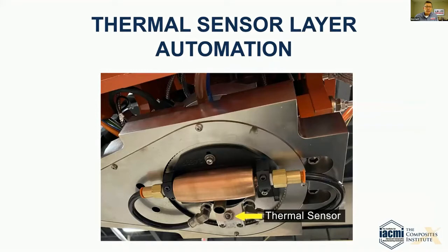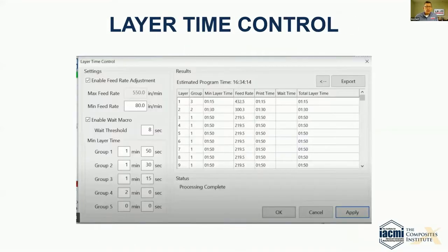And what this is, they use a small thermal sensor that is right in front of the nozzle as it's depositing material. So it's looking right at the substrate at the instant before material is deposited on it. So you know exactly what temperature the substrate is before you put fresh material on. Since the deposition head rotates to have the wheel follow the deposition, you always are looking right in front of the nozzle.